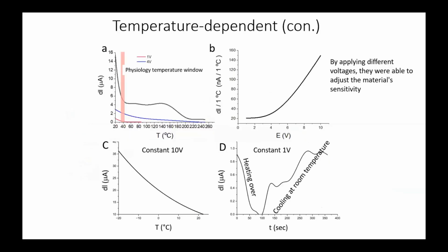But if we apply a higher voltage, more than 1 volt, we have here this is 1 volt, this is 4 volt, and this is 10 volt. You can see that the electrical response gives a slower degradation if we apply a higher voltage.